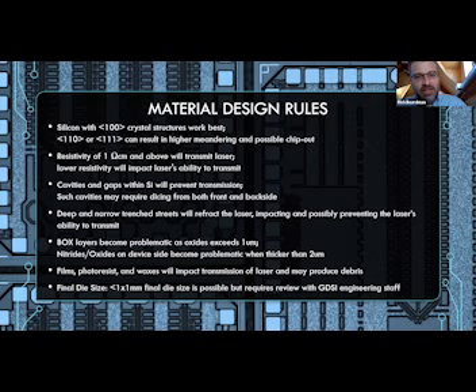Things such as cavities and gaps within the silicon will prevent the laser transmission. What the laser is looking for is a uniform flat surface of silicon across the wafer in order to transmit the stealth dicing layer underneath the silicon. If we have cavities or gaps, that laser light transmission will be interrupted. And then again, going to the post singulation step, the tape expansion step, we won't have uniform singulation there.